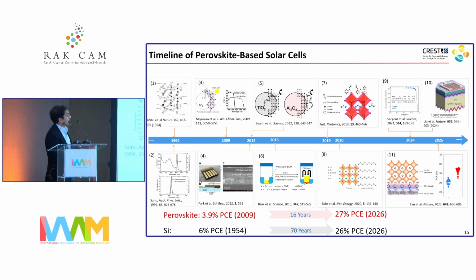I think our biggest contribution to the field happened when we started showing that large single crystals of these materials can be grown in a very simple fashion and still maintain very low defect densities comparable to optoelectronic silicon. This was surprising because back then people thought diffusion lengths in perovskites were around a few hundred nanometers. We showed that it was in the tens of microns at least.